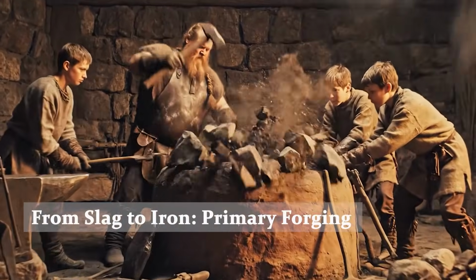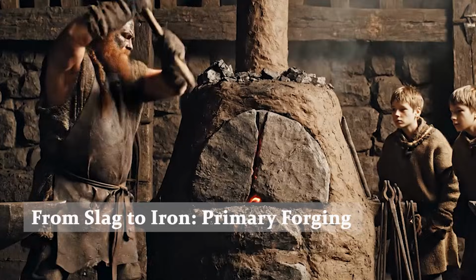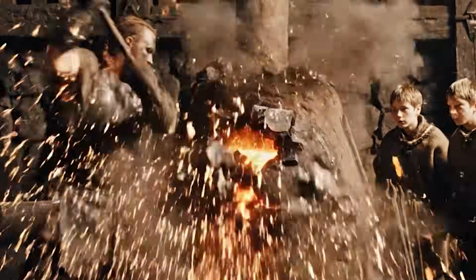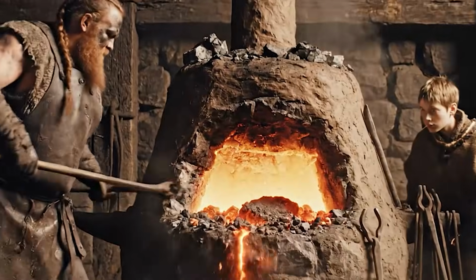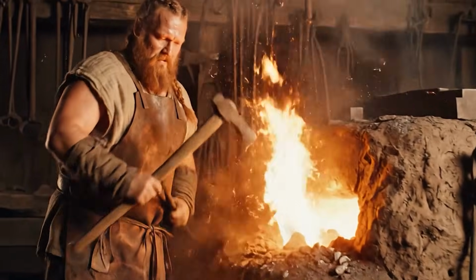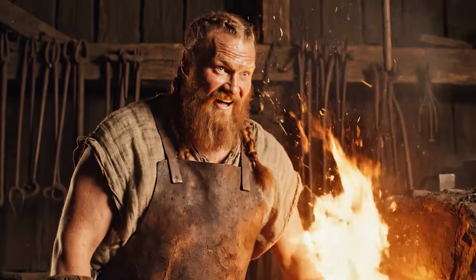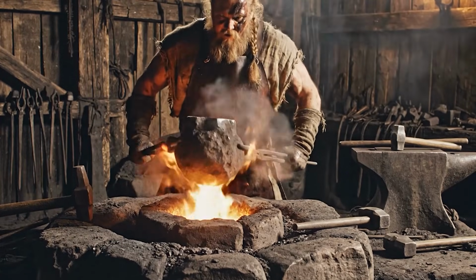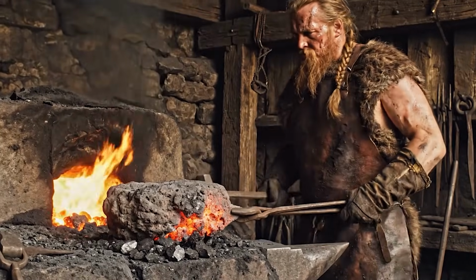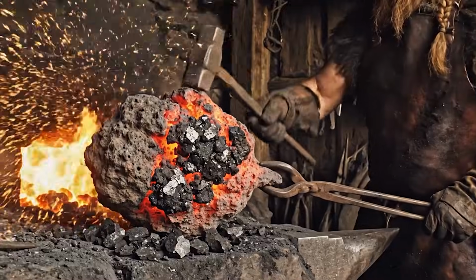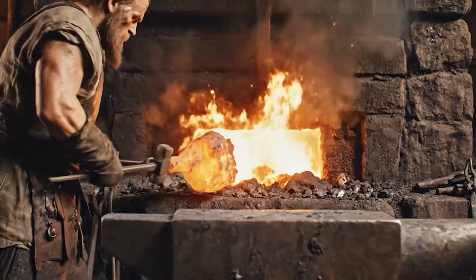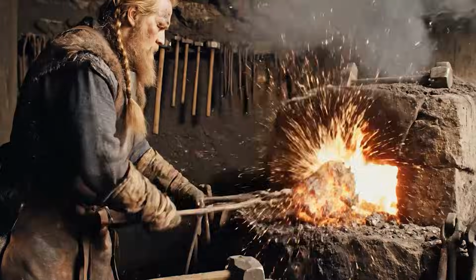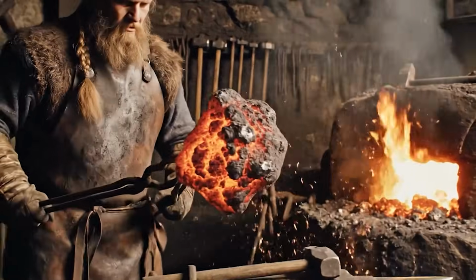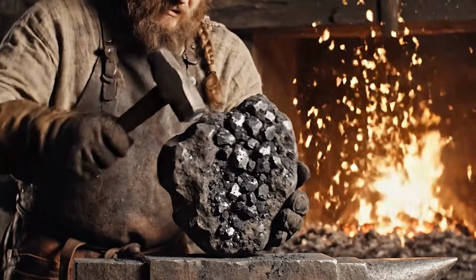After long hours of fiery work and agonizing waiting, the most exciting moment arrived. The craftsmen dismantled the wall of the cooled or still hot furnace to extract what they had set out to achieve. At the bottom of the furnace, mixed with the remains of coal and solidified slag, lay the result of the smelting. It was the so-called pig iron, a shapeless, porous piece of reduced iron.